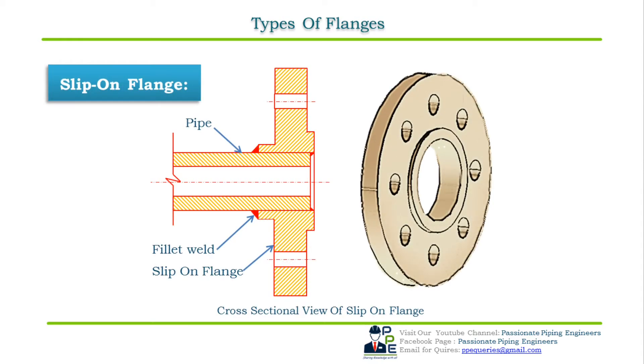The next type is the slip-on flange. A slip-on flange is connected to the pipe or fittings by two fillet welds — one executed inside and the other outside the cavity of the flange — to provide sufficient strength and prevent leakage. The pipe is set back from the face of the flange at a distance equal to the wall thickness plus 1/16 inch. Slip-on flanges are manufactured with an inside diameter slightly bigger than the pipe OD so they can slip over the pipe. The calculated strength under internal pressure is about one-third that of the weld neck flange, and fatigue life is also one-third.